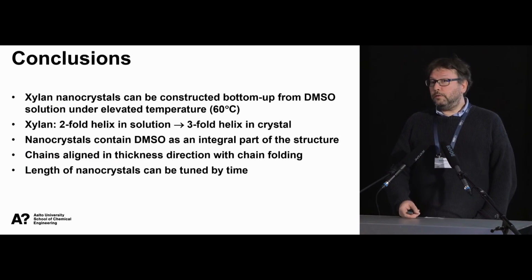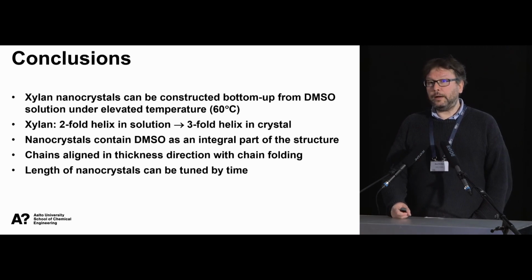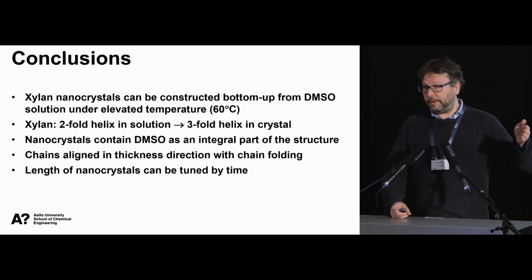So to conclude, the xylan nanocrystals can be constructed bottom up from dimethyl sulfoxide solution under elevated temperature, at 60 degrees specifically. The xylan is, as you may know, a twofold helix in solution, but it's a threefold helix in the crystal, and the DMSO is an integral part of the structure, the DMSO molecules in the crystallized structure. And importantly, the chains are aligned in the thickness direction